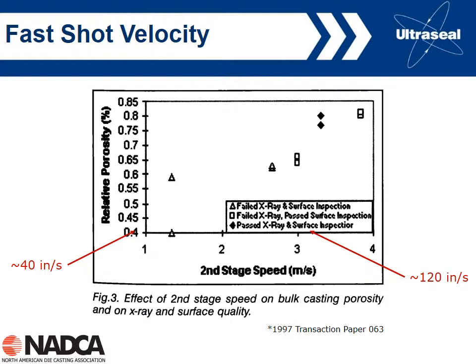If we go even faster, we get to these white squares up here. If we look at the legend for the white squares, we failed X-ray but passed surface inspection. So maybe what's happening is that we're injecting the metal so fast that we're blocking the vents very early in the casting process, allowing us to trap more gas and fail X-ray, but again, by going at high speed, we're getting a good surface finish in our casting.